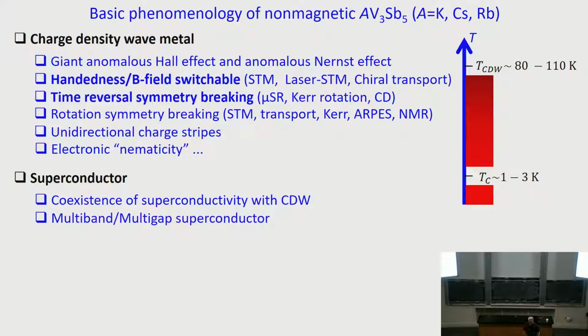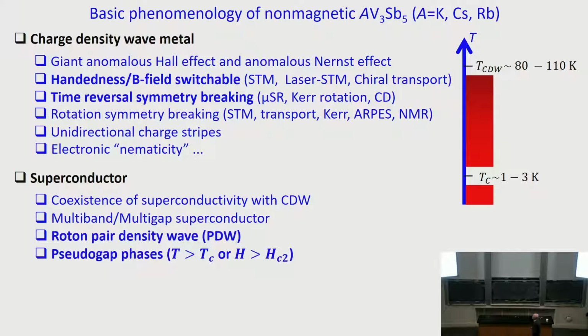It's a many-orbital or multi-band superconductor. But more interestingly, the superconducting state exhibits a kind of pair density wave order. That is, the Cooper pairs seem to carry a non-zero center of mass momentum. Right? And there are pseudo-gap phenomena also both above superconducting transition and at low temperature with the field that is above the critical field for the superconductor. So in both cases, you still see pseudo-gaps remaining outside the superconducting state.